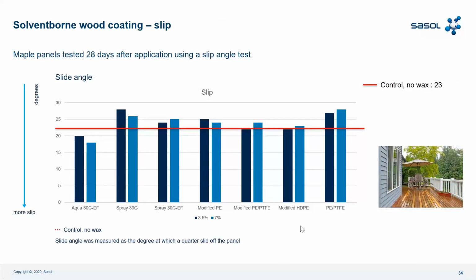So the slippery test, more slip means the lowest value, again. The control without wax is 23. So you see that Aqua 30G-EF at 3.5% achieves a great result, around 20, and it is followed by the other waxes, Spray 30G and Spray 30GF. So Aqua 30G-EF is the only one below the control, so very good slippery in a solvent-based system. So a promising extra fine modified wax.